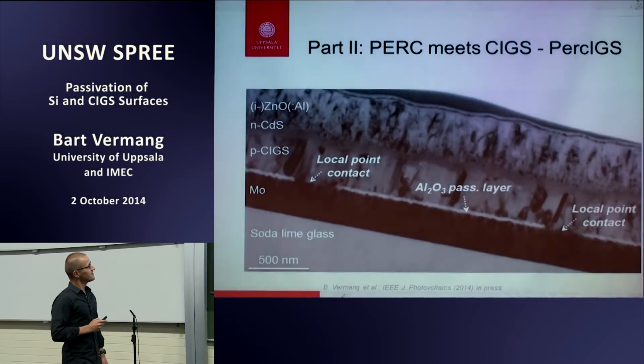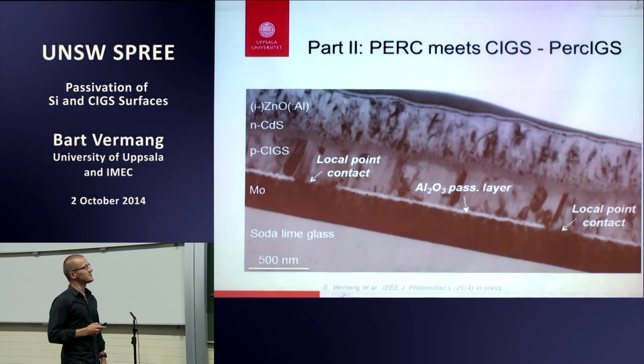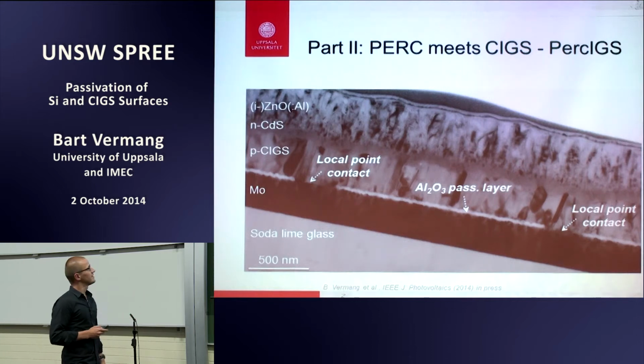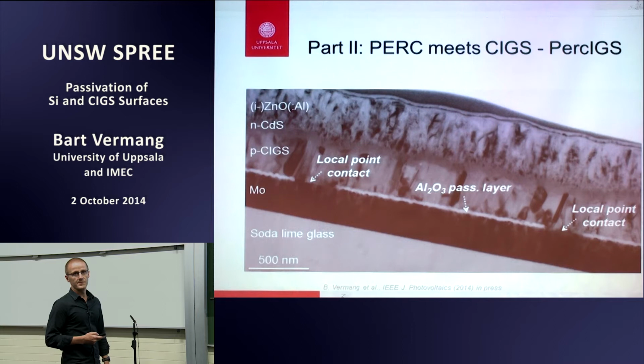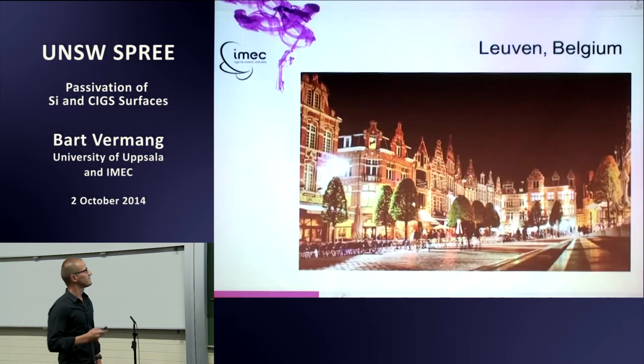And then the second part: in my last 2 years, I was a postdoc at the University of Uppsala, where I have been trying to implement something very similar. So an aluminum oxide passivation layer at the rear, between the molybdenum rear contact and the CIGS absorber layer, having openings as well. In this case, we're talking about nano-sized openings. In the last case, we were talking about micron-sized openings, of course.